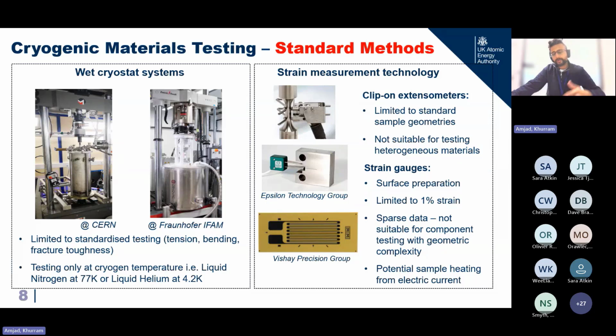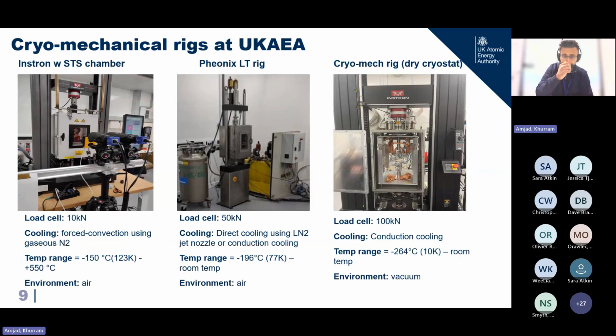But the problem with it is if you have a material which shows heterogeneous strain fields, then you're limited by the number of data points you can get, because there is a practical limitation to the number of strain gauges you put on your sample or component. So ideally, we'd like to see a non-contact technique where you should be able to see the full field strain fields. And this is what we try to work on.